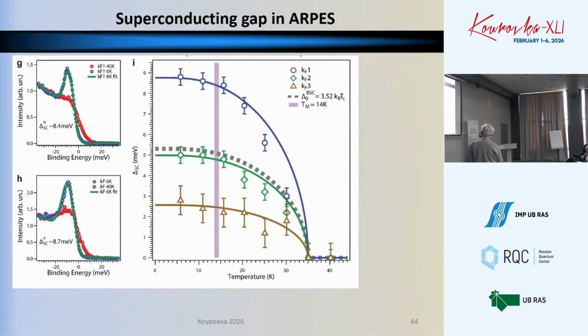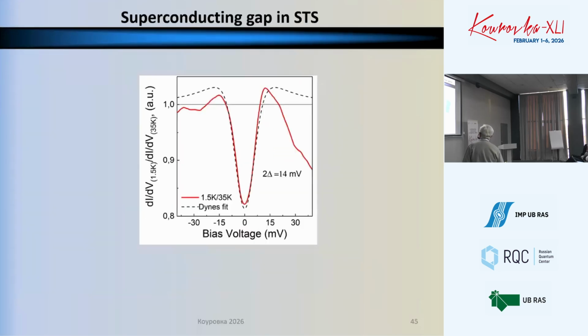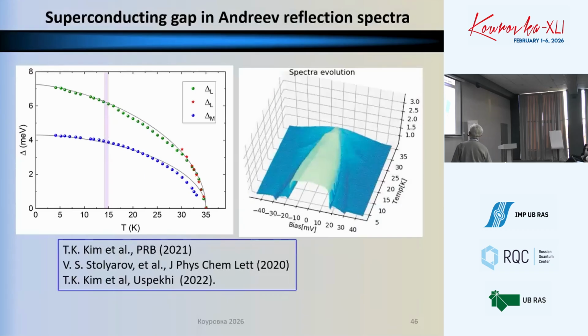The gaps extracted from this ARPES measurement didn't show anything at the temperature of the antiferromagnetic ordering. This was surprising. Scanning tunneling spectroscopy didn't help, but we did Andreev multiple reflection with more resolution to test what is going on in the vicinity of the antiferromagnetic temperature, and we actually find no changes. So the superconductivity seems to completely ignore magnetic ordering. This was strange, and this is one of the issues I want to discuss.